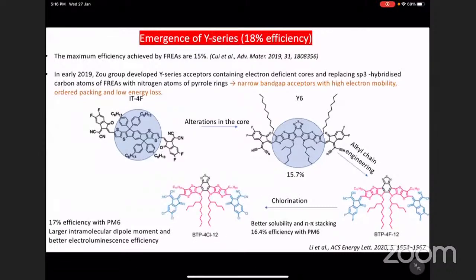The whole idea was how do we use these chemical structures to induce crystallization and change the packing and nanomorphology by stacking of these systems at the intermolecular stage. And that could make huge changes in the overall efficiency numbers, going all the way from 10% to 17-18% with this PM6 system. These are the same family, with various different acceptor molecules with a little bit of chemical modification by chlorinations, by changing the alkyl chain length. So this is all a guided path. It's not like just random, today I make this molecule and let's try it out.